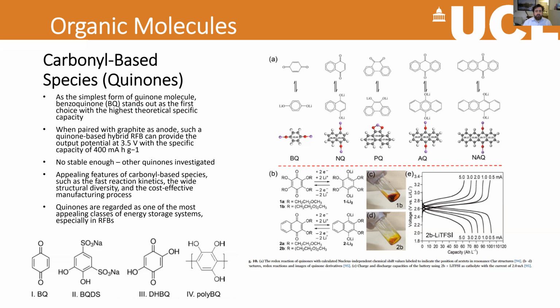One of the key benefits here actually is that you can have quite a high output cell potential, 3.5 volts. And because the voltage of the cell is related to the energy that you get from each electron transfer, remember that that's dependent on the voltage. And so higher voltage will just automatically give you a higher energy in your system. It does mean though that you have to go to different types of electrolytes. So because water has a breakdown voltage of 1.2 volts, anything above 1.2 volts, you have the potential of splitting water into hydrogen and oxygen, which obviously you don't want to do in these systems. So you then have to use a slightly different electrolyte and solvent, which might be more expensive or might be environmentally friendly, for example.